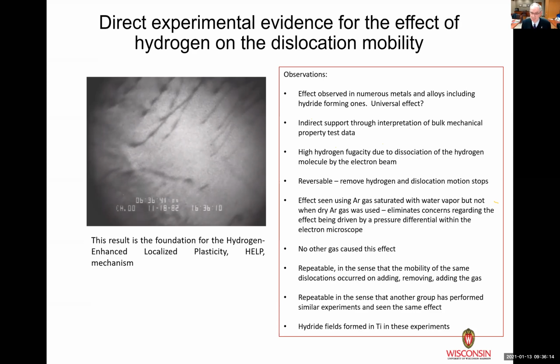There was no effect. So then we had the very clever idea that why don't we use argon gas as a carrier gas, but before it enters the microscope, let's fully saturate it with water vapor. So of course we bubbled argon gas through a bubbler full of water into the microscope column. I wouldn't say it was my best experiment ever, because putting water vapor or water into an electron microscope column doesn't make you any friends with the rest of the microscopists, but that's what we did. So what happened?